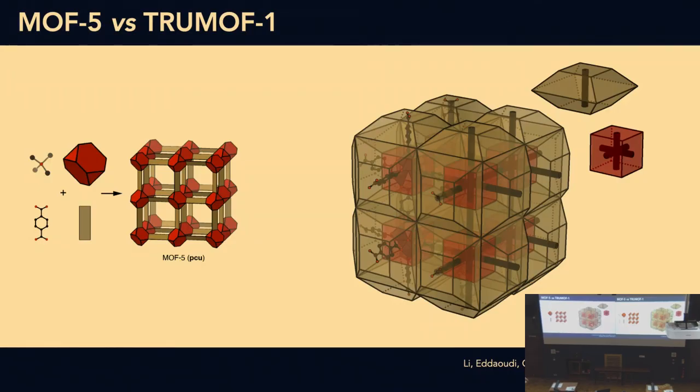How do I think about this in terms of a tiling? Well, technically I just split this into what's called the Voronoi tessellation. And all Voronoi does is say, for each point in space, you work out, are you nearest a node or nearest a linker? And the volume of space that is nearest a given node or a given linker will form a three-dimensional block.